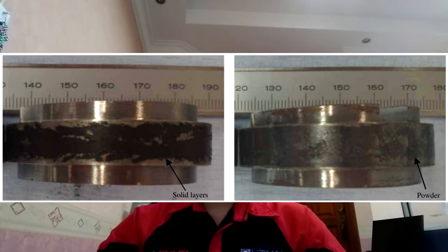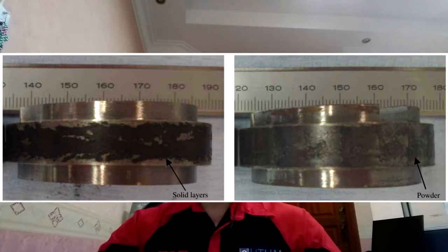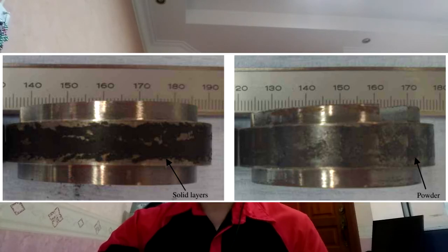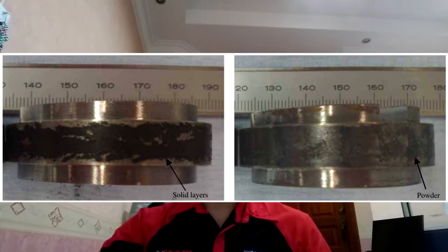In initial sliding, when the slip is low, the layer will be removed slowly, which we can observe on the left, while on the right, when the slip is high, the layers will turn into powder, which can be easily removed even by finger, just rubbing on it, and the powder will be removed.